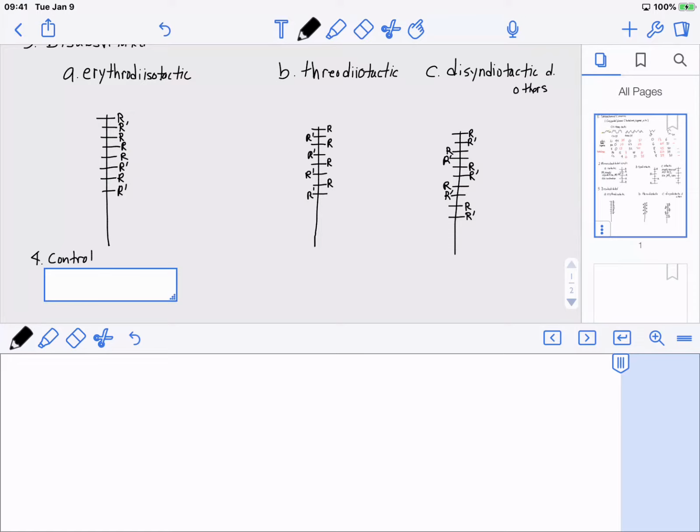But anionic polymerizations in apolar solvents can be very specific. So if the polarity is high, you get a lot of separation between things, and consequently you don't get specificity, but where things are kind of paired, charges lumped together a little bit, things are close together, there you can get stereochemical control.